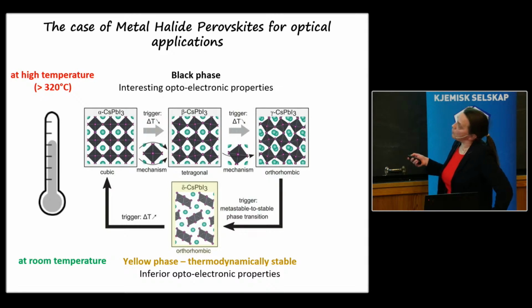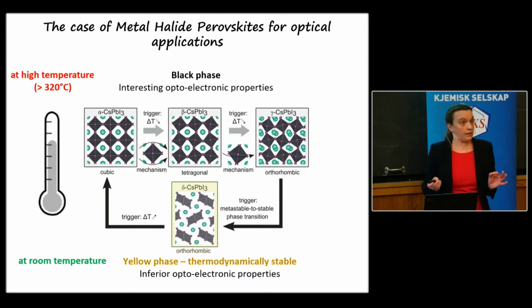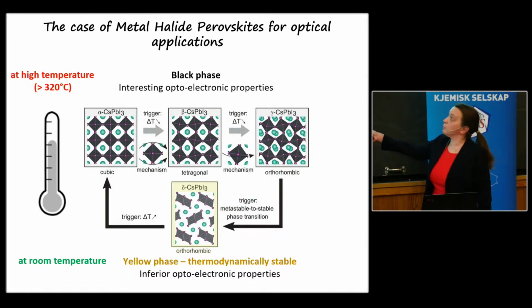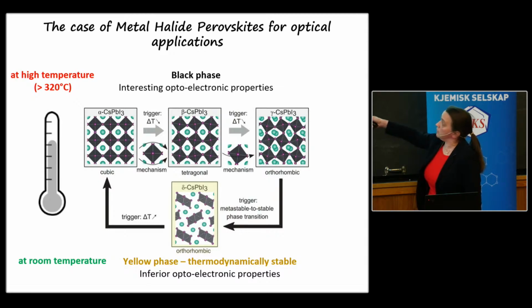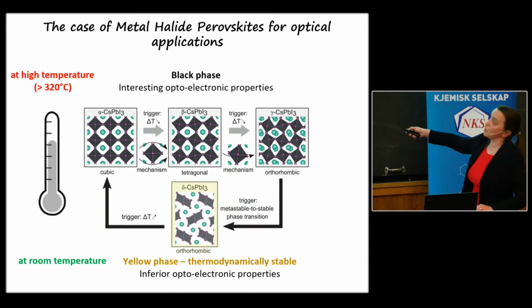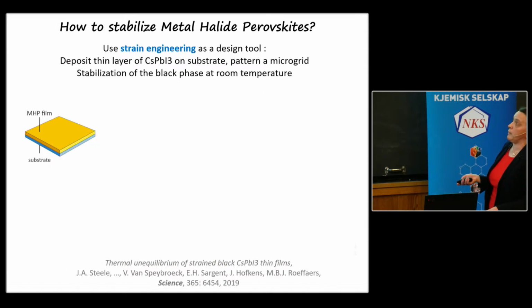Here you can see some of the phases that were observed. These are the optically active phases, close to this nicely ordered material. You find them at high temperature. If you bring them to low temperature, this is a thermodynamically stable phase, we see this disordered phase, which we call the yellow phase. So there are two things to remember. We have the black phase, which is the active phase, the one that we want, and we have the yellow phase, which is thermodynamically stable, which we find at room temperature.